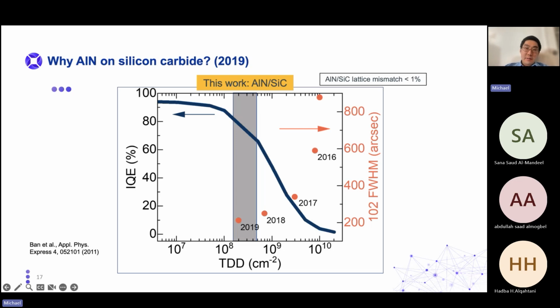With silicon carbide and the flip chip process, we can remove the silicon carbide through a dry etch, which is not as easily done with sapphire, and then that would allow for the light to escape, and there would be no aluminum nitride to substrate interface left for total internal reflection. So that was the main selling point behind our initial ideas.